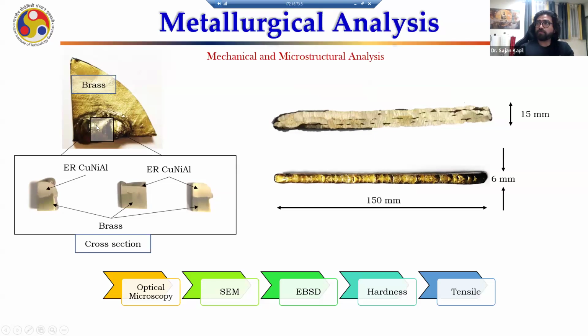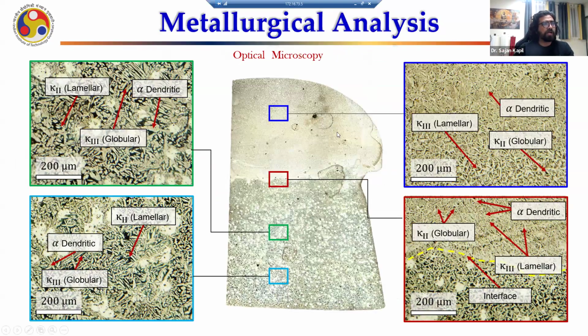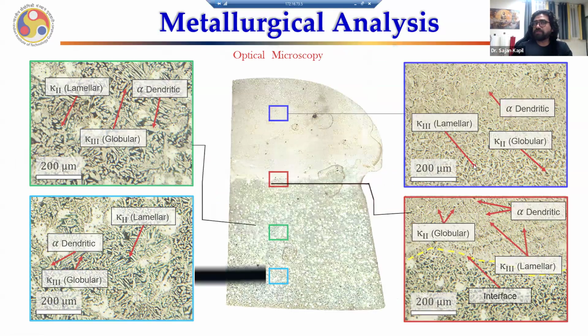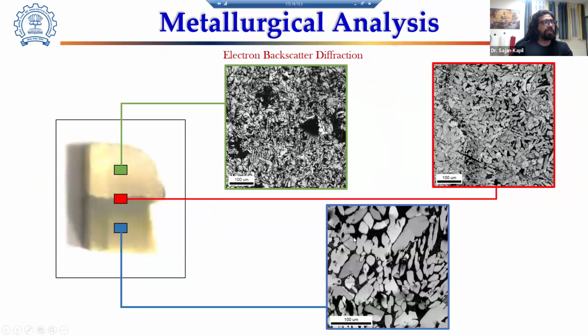We deposited first. Of course, we took a broken part because they made a deliberate cut, like I said. We deposit material onto that and did the testing. We find that the grains in the deposited part are quite smaller as compared to the base, because the base is the casted one. You see in detail the EBSD for the same, the portion over here, and at the interface you can also see the nice merge of the grains. Of course, there is no very sharp change observed either.